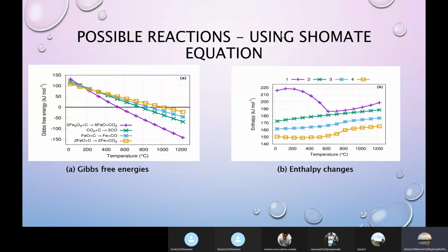It should be noted that the combination of the three equations will imply the generation of carbon monoxide and dioxide in the form of gas. This would result in a great loss of mass in the sample, in accordance with the DTA analysis, at 1056 Celsius, the first stage.